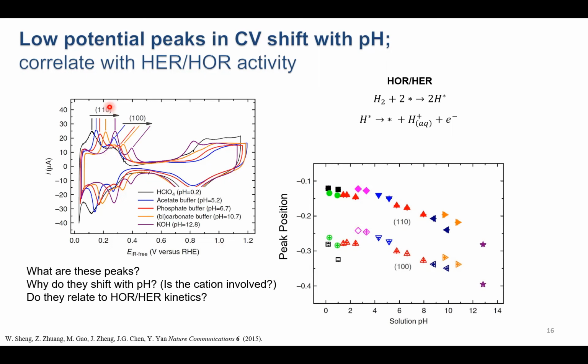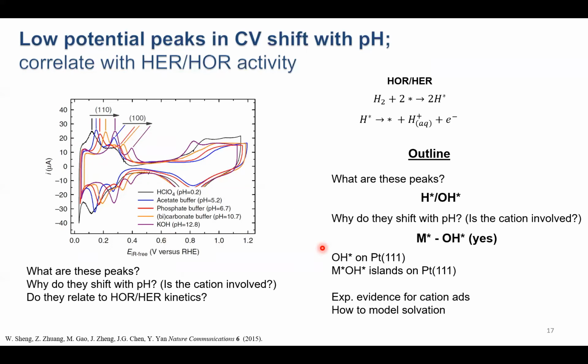We also know it's adsorption on stepped sites on the polycrystalline platinum electrode, in particular 110 steps and 100 steps. It was traditionally assumed that this corresponded to hydrogen adsorption. We'll show actually that it's not. And so we want to identify what is going on in these peaks. Why do they shift with pH? And is that somehow related to the presence of a cation sitting close to the electrode surface?